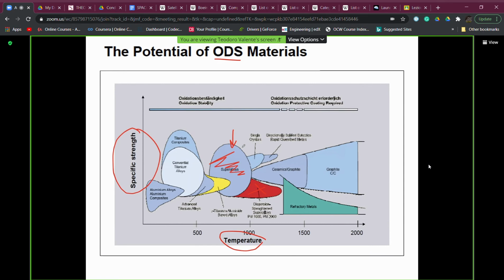But actually, to come to the conclusion, the possibility to modify the microstructure of the conventional and known nickel-based superalloys, for example with the gamma prime phase, with tailored formation of carbides and addition of special alloy elements, still makes the superalloys the best performing in terms of specific strength, even though the maximum working temperature is about 200 degrees less than what can be allowed by ODS materials. But the standard solution now is still using nickel-based superalloys, conditioning them with the use of thermal coatings.